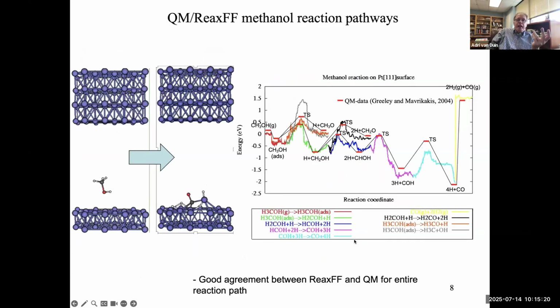So the speciality of ReaxFF, and that's really where we're focusing quite often in development, is barriers and intermediates. So we really try to get reaction coordinates reproduced from DFT. Here's an example of a methanol reaction to carbon monoxide on a platinum surface.